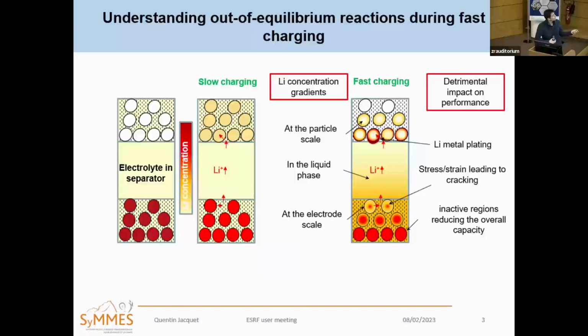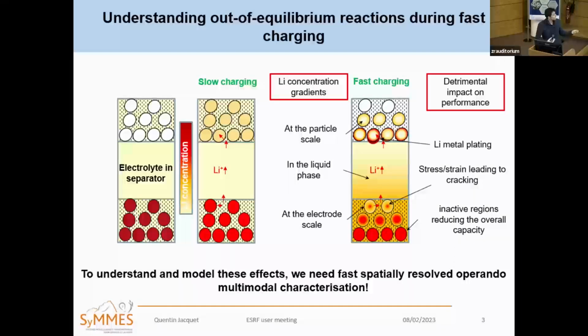For example, if you try to stuff lithium into graphite too quickly, you're basically going to saturate the surface with lithium, and the next lithium you want to put in is actually going to plate lithium metal. And this lithium metal is going to react with the electrolyte, and you're going to lose lithium, which is not going to be available for the reactions anymore. Another effect of this fast charging would be losing part of your electric capacity just because this part of the electrode is inactivated. So if we want to understand better what's happening, model it better, we need to look at it better. And for that, we need spatially resolved and fast operando experiments.